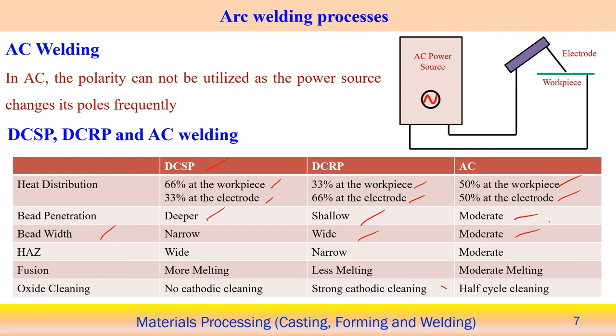Heat affected zone: DC straight polarity gives a wide heat affected zone because maximum heat is generated on the workpiece. Reverse polarity gives a narrow heat affected zone, and AC current gives a moderate one. As for fusion, the effect of fusion will be more in case of straight polarity, which means more melting on the workpiece side. Less melting will be there with reverse polarity, and using AC current, moderate melting will be there.